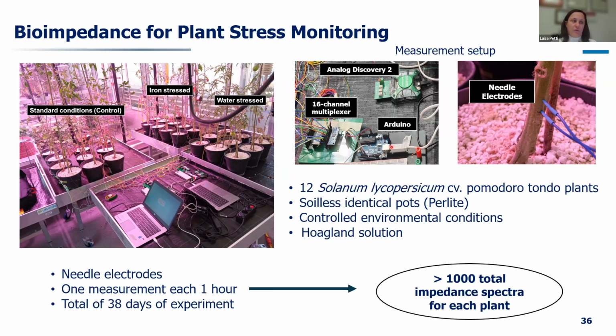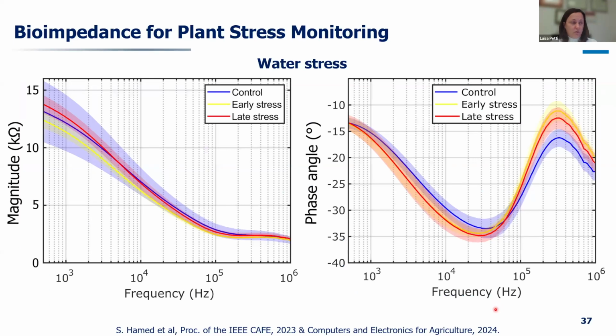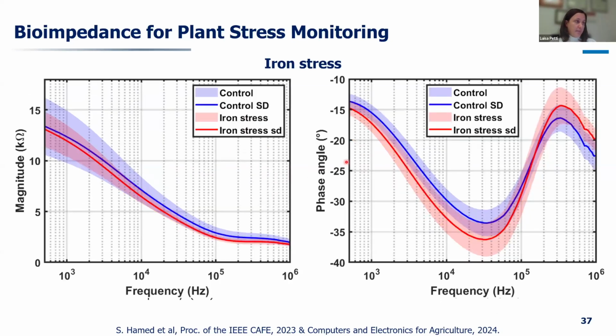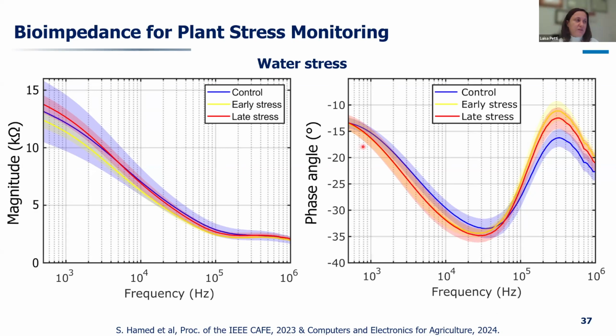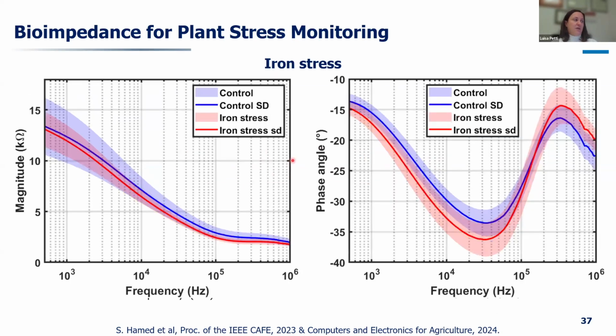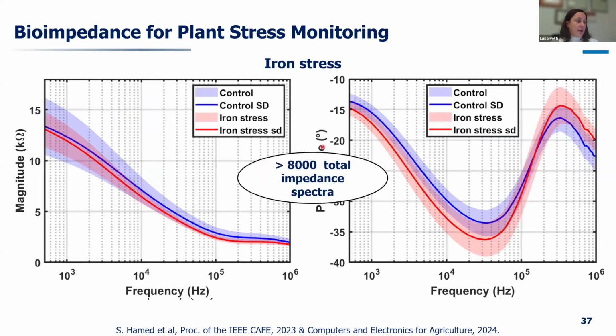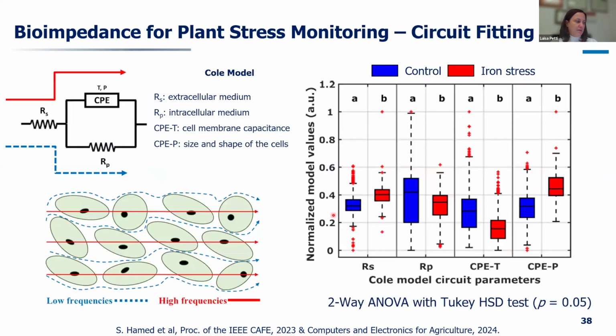Again, Analog Discovery, multiplexer, Arduino, and with this, measurements were taken every hour for a total of 38 days of experiments, acquiring more than 1,000 impedance spectra for each plant, so lots of data. You see here the magnitude and phase for control, early stress and late stress, in the case of the water stress, and in the case of the iron stress, acquiring really more than 8,000 spectra in both cases.